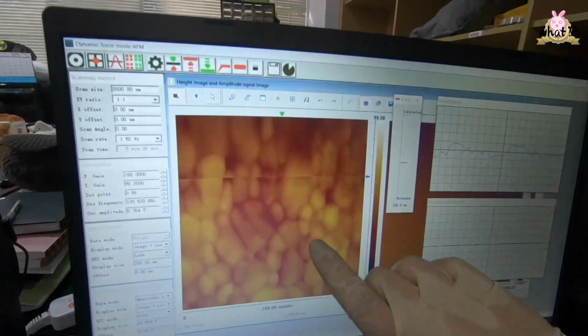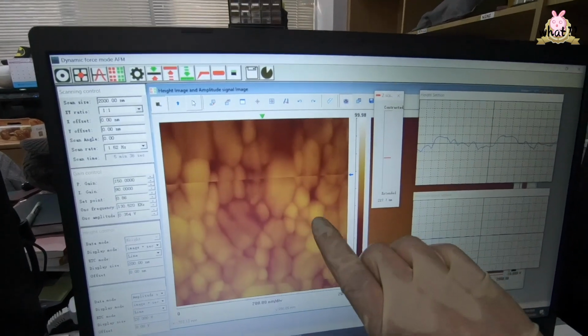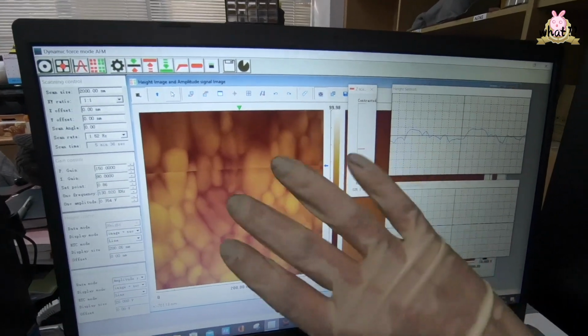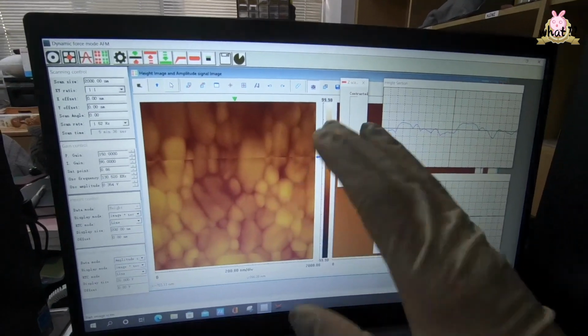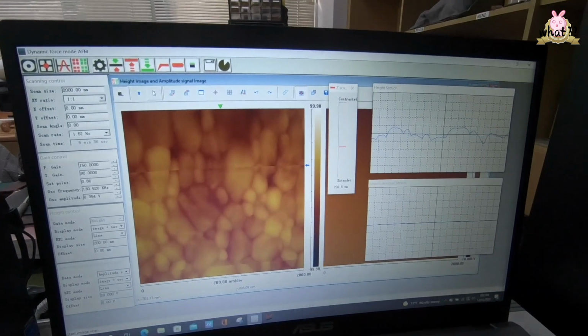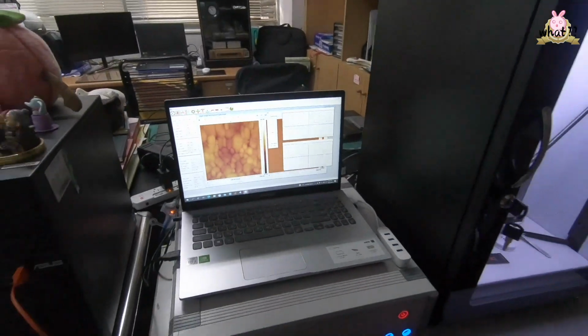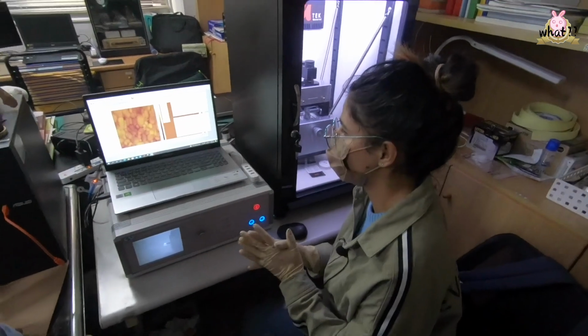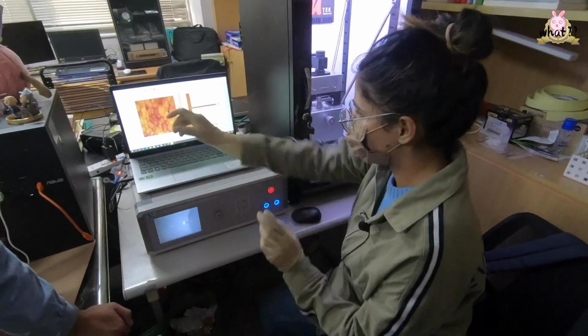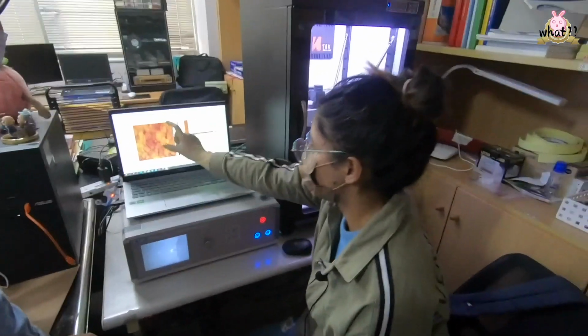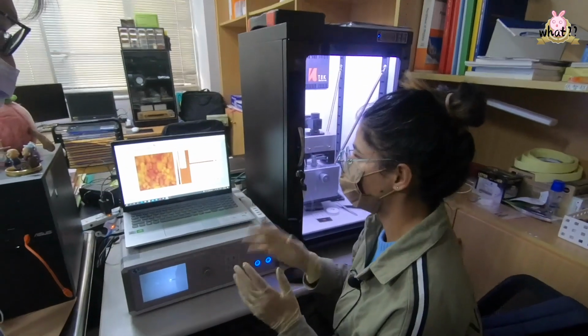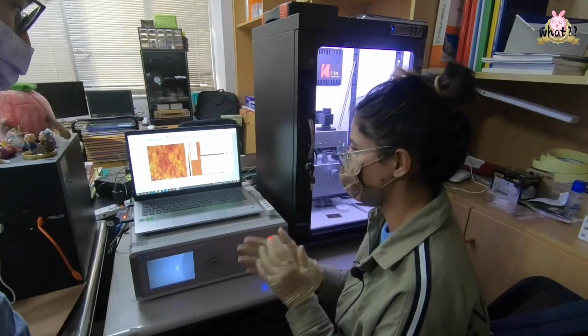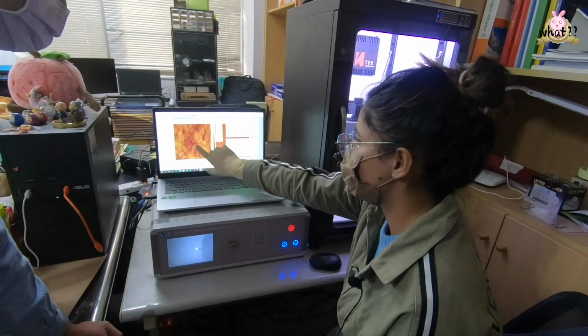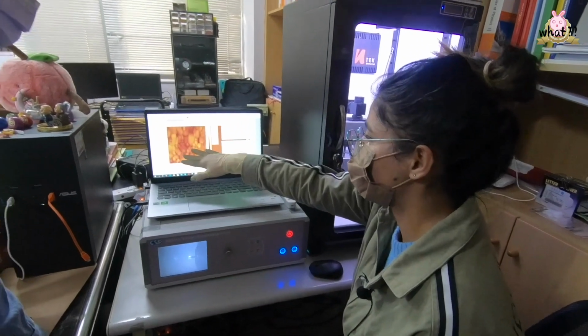You can see some small grains and some larger grains. Because of them, the roughness changes. From these pictures, we use them to find the roughness of our samples and the different grain sizes. Sometimes the grain size is big, so we will know that the condition used is better. But if the grain size is increased, it's more rough.